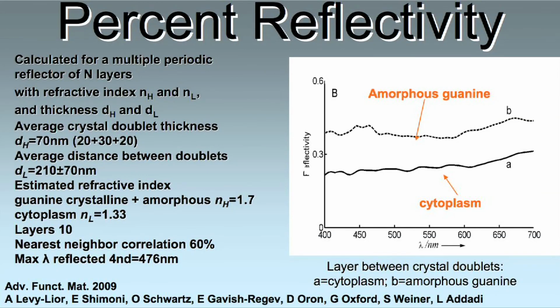And now, again, we can calculate the whole thing. We can simulate the reflectivity. And we have the thickness of the crystal doublet. We have the distance between the doublets. We estimate, we don't have a precise measurement yet, that if this is a sandwich of guanine with crystalline and amorphous layer in between, then the index of refraction of the composite material should be around 1.7.